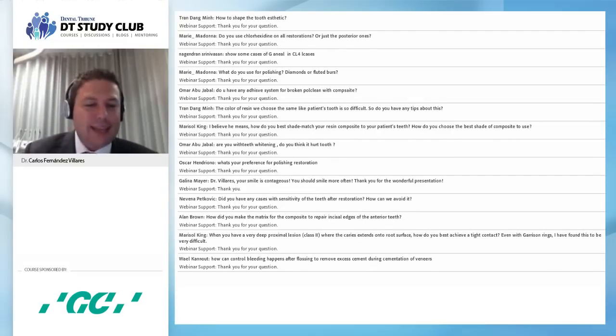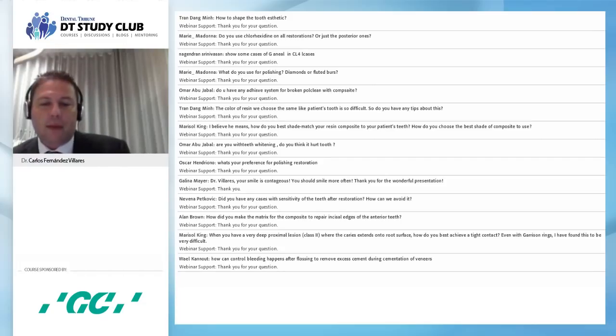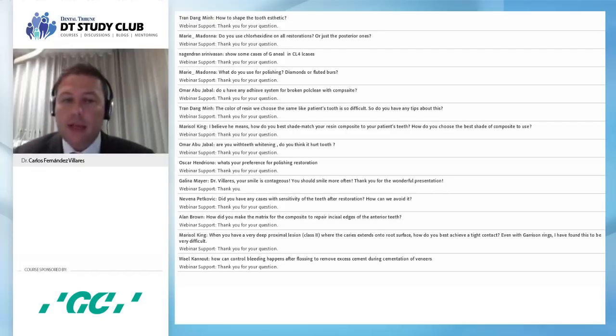My patients are exactly the same as all of you, and they have problems with bleeding, and they have gingivitis, and we try to do our best in our practice, but sometimes we have that problem. So what we do is try to treat every patient who is going to have problems with bleeding. Use a rubber dam, thick rubber dam, and then you will have no problem. And if not, you can use retraction cords with some retraction paste, and you will have very good success.